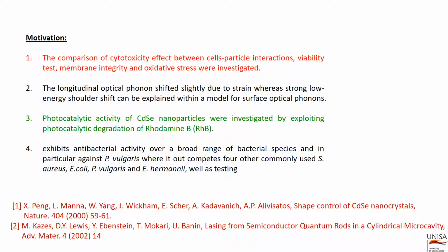So, I'm going to present the motivation of my research work. In the first point, the comparisons of the cytotoxicity effects between cell-particle interaction, viability test, membrane integrity, and oxidative stress were investigated. The longitudinal optical phonon shifts slightly due to strain, whereas a strong low-energy shoulder can be explained within a model for surface optical phonons. In the third point, photocatalytic activity of the cadmium selenide nanoparticles was investigated by exploiting photocatalytic degradation of RhB, which exhibits antibacterial activity over a wide range of bacterial species, in particular against P. vulgaris, where it outcompetes other commonly used ones such as S. aureus, E. coli, and E. hermannii, as tested in the present work.